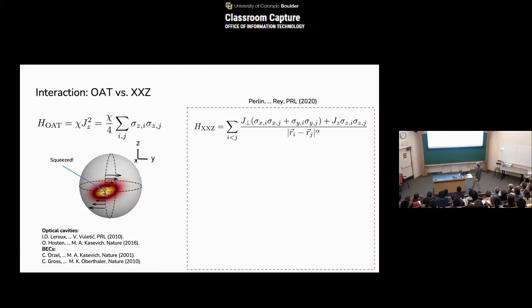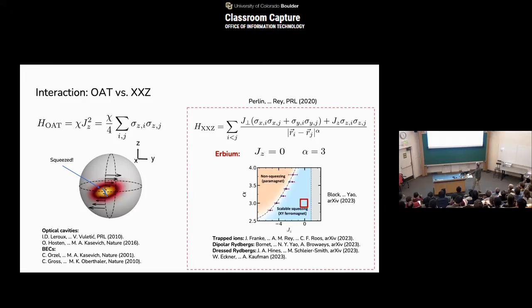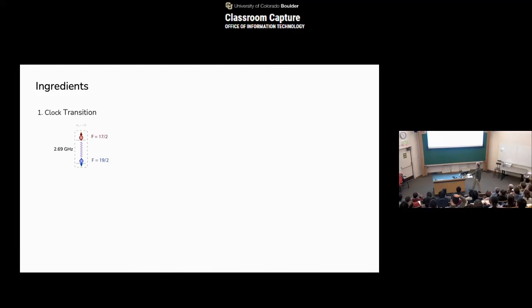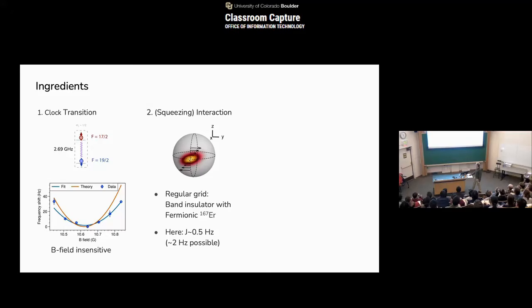But Anna Maria Rey figured out, wait a minute, I can actually also do this with long-range-ish interaction. You don't need all-to-all interaction. And you only need moderately long range, depending on the dimensionality, actually. You need different kinds of fall off of interaction. Let me skip all the details other than saying that the prediction was that with dipolar interaction in 2D, you could actually get nice squeezing. And so we started to try this. We have a clock transition that is very magnetic field insensitive.